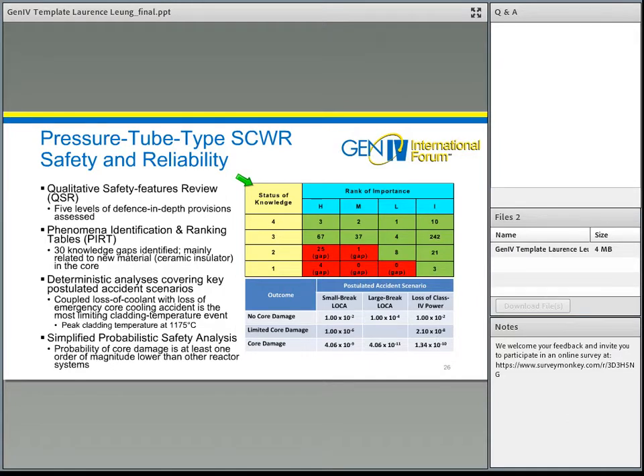So they identified 30 knowledge gaps in this assessment, and the majority of the knowledge gaps are related to the new materials used in the core, especially the ceramic insulator that insulates the high temperature coolant from the low temperature pressure tube, and also the moderator. And they applied a deterministic analysis covering a lot of postulated accident scenarios, and they found that the coupled loss of coolant with loss of emergency core cooling accident is the most limiting cladding temperature event for this concept. The peak cladding temperature is predicted around 1175, which is close to the design limit, but still below the melting temperature of the cladding.